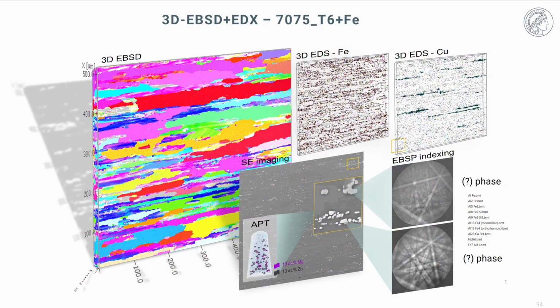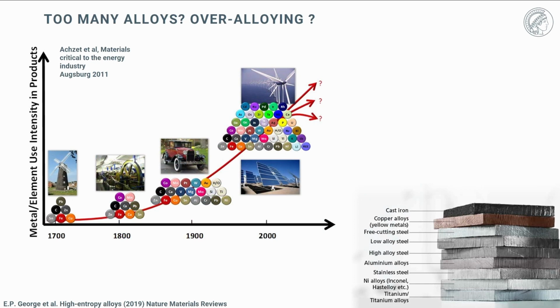And of course in aluminum alloys, particularly the iron is a big problem because it forms also brittle intermetallic phases, and one can, for instance, when you tolerate higher iron content in aluminum alloys, try to change these intermetallics by further alloying in order to make the overall scrap containing alloy more robust towards recycling.